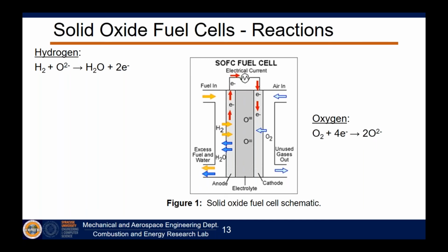And electrons coming over from the anode side go through an oxygen reduction reaction to create oxygen ions, which are here. At high temperatures, there's oxygen vacancies within that electrolyte. And so those oxygen ions are actually able to jump from vacancy to vacancy through the electrolyte. They come over to this side, to the other triple phase boundary where the anode electrolyte boundary is, and they can combine with fuel through this half reaction. So for example, hydrogen and an oxygen ion can form water and the two electrons that are needed to complete the circuit. And then the electrons are ultimately going through the external circuit here.